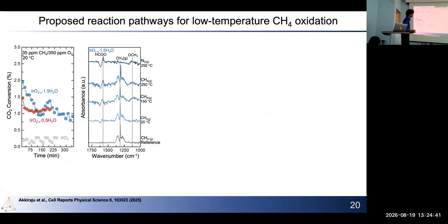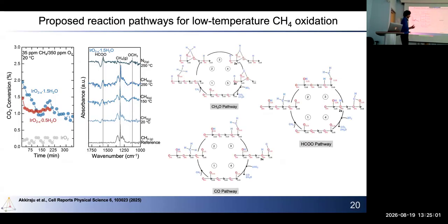We wanted to see if this is really true, if methane was really getting activated, and then we turned again to IR spectroscopy. We could see the formation of reaction intermediates starting all the way from 20 degrees onwards. Going to 250, we see a strong formate peak, which is one of the major intermediates in the methane reaction pathway.